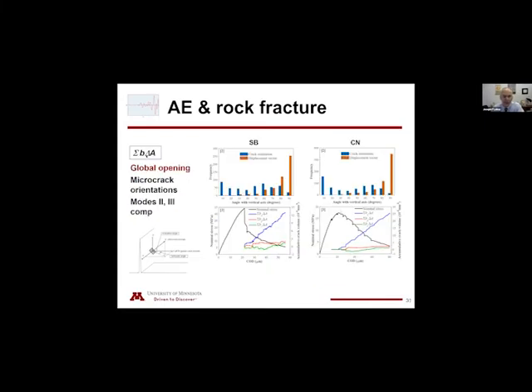So these are now the results of the B delta A components by decomposing that vector, of course, this quantity that we give the vector quantity to, the B, in the X, Y, and Z direction. So this is the global coordinate system where X is normal to the fracture that's developing in this rock. And you see the dominance, as you would expect, for the analysis of these crack events. It is interesting to see not only a Y component, but a Z component that is taking place out of plane, right? Certainly these values on the order of 2 × 10⁻³ are much smaller than the BX component, that is the opening. And it's consistent for both beams. And in fact, you see a larger opening just because we have more events for the center notch beam.